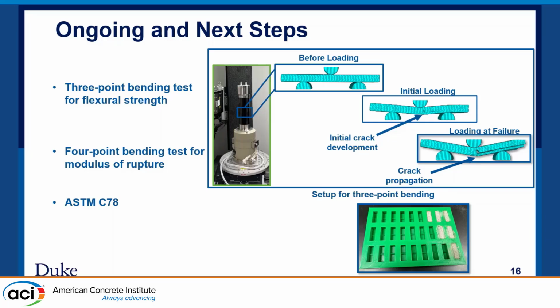While doing this experiment, we have to have very small samples for this test, and we use 3D printed molds for the preparation of samples. But we face the problem of getting the samples out of those molds. Even if we could get the samples out of those molds, they would break, and that would hamper our test. So we are looking for alternative molds we can use for the samples we have to use for this machine.